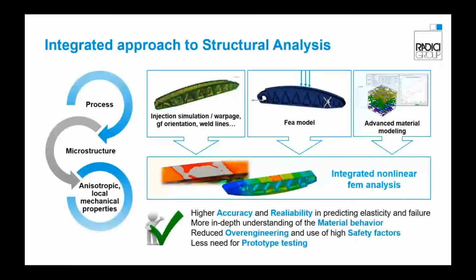Practically, outputs coming from the process simulation, such as fiber orientation, welding lines, residual stresses, and warpage, are mapped onto a structural model with a dedicated software. Then, structural simulation takes into account for each point of the part a specific mechanical response. This leads to a more in-depth understanding of the material behavior and consequently to the reduction of over-engineering and the use of high safety factors.